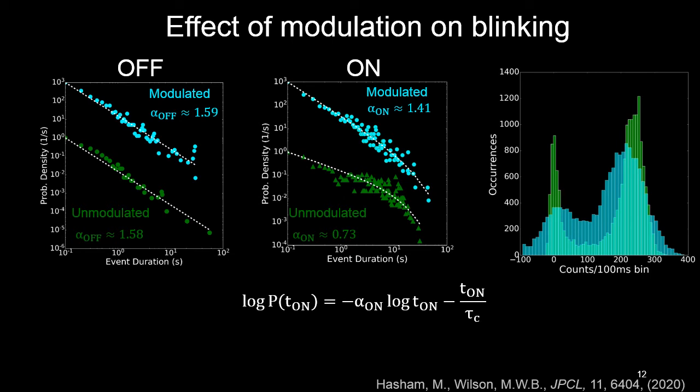Just to make sure things were real, we first pre-screened all the intensity traces, and if we found any durations longer than 10 seconds in the on state, we used the 100 preceding and following points that didn't have any long on times to subtract off a local background. This was only relevant for about 0.6% of the cases. We did our best to be careful because when you get a bigger slope in the data, we have suppressed on times and we really wanted to make sure the effect is real.